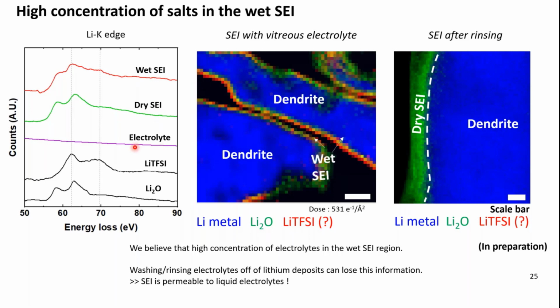We found from cryo-EELS that there exists excess lithium salts in the SEI regions when we preserve liquid electrolyte. You can see in the red curve the fine structures of the lithium K-edge spectrum of wet SEI. This appears to be a combination of lithium oxide here and lithium TFSI. However, if you prepare another SEI after rinsing excess electrolyte, the lithium K-edge spectrum of dry SEI contains only lithium oxide. And this suggests that if we want to perform intact SEI analysis, we really want to preserve liquid electrolytes. Otherwise, you can readily omit some information.